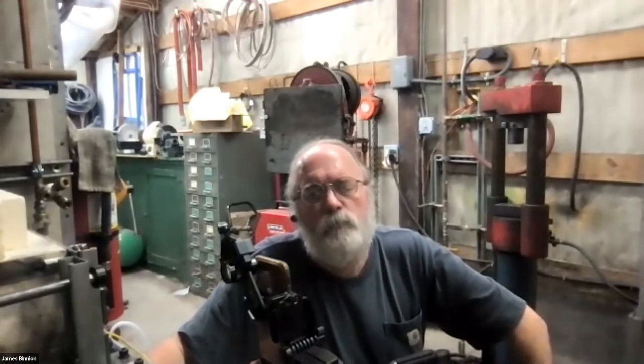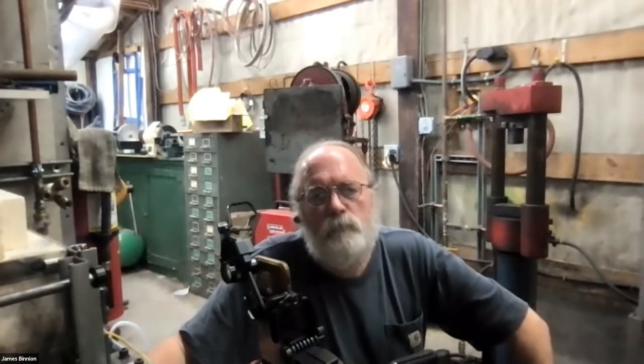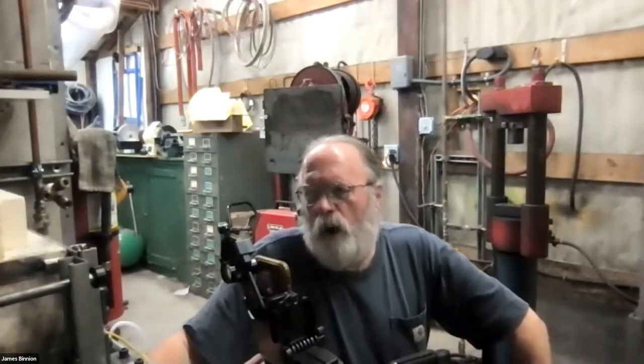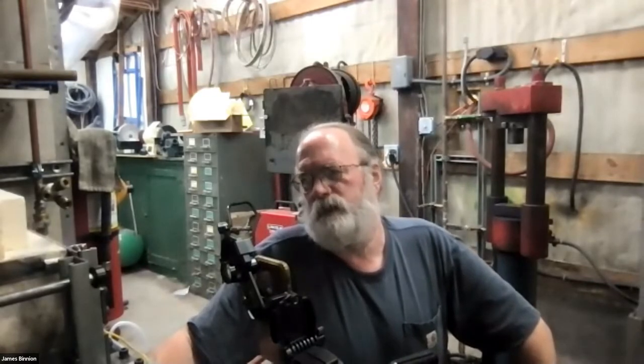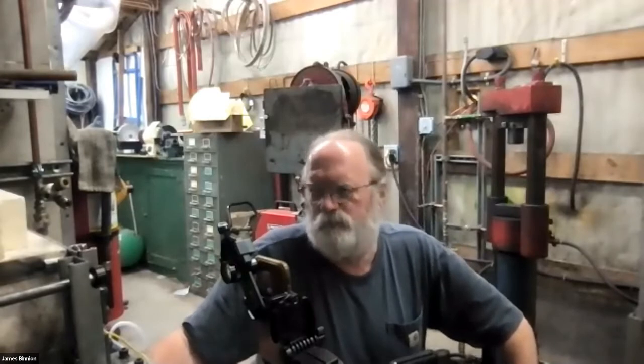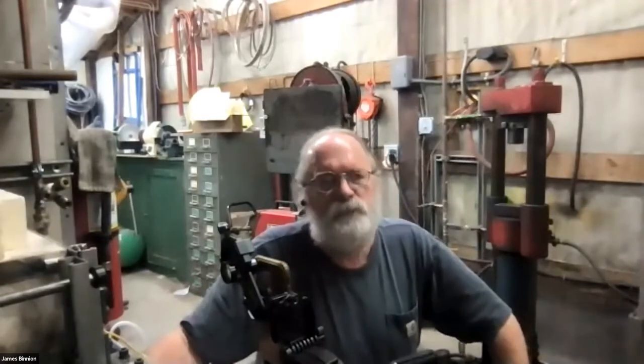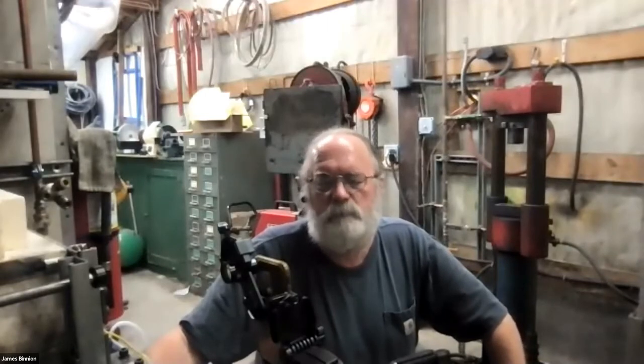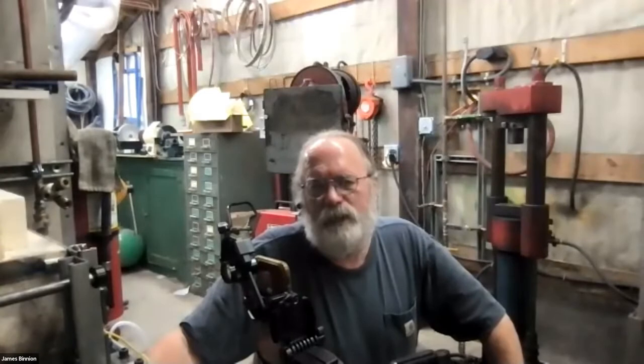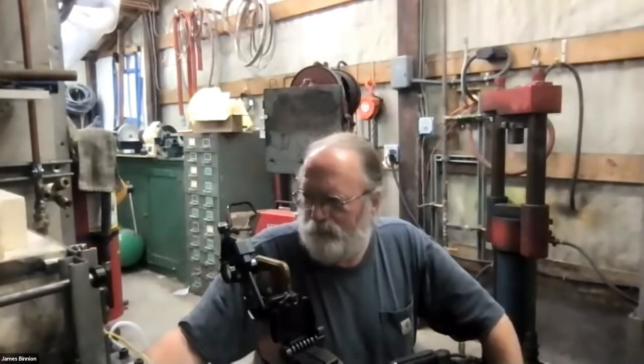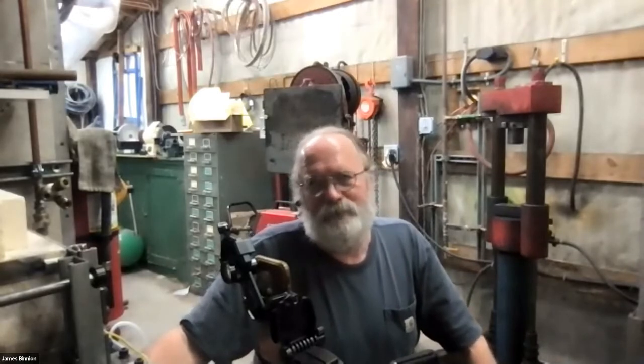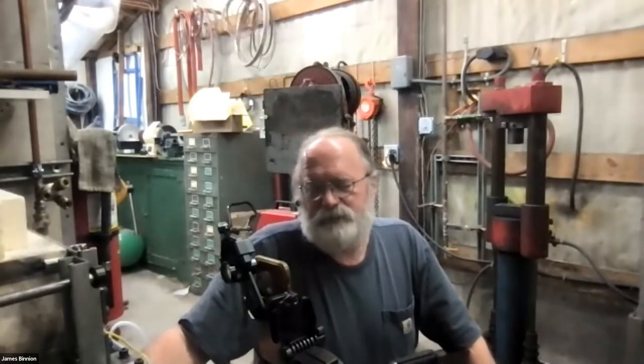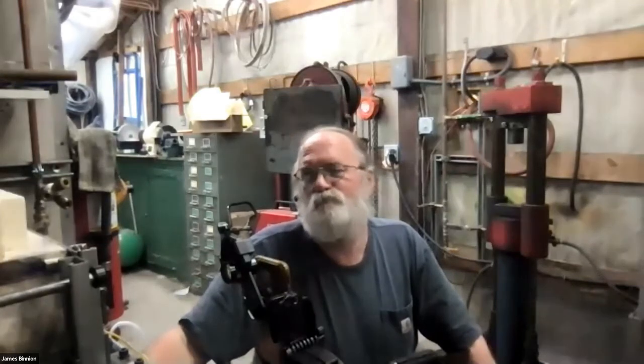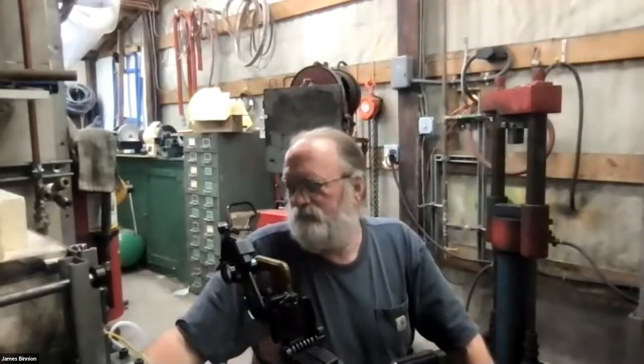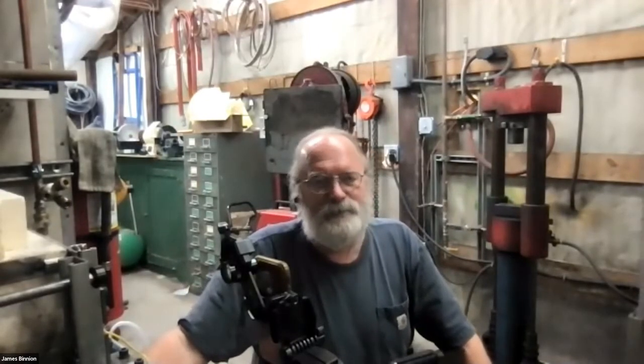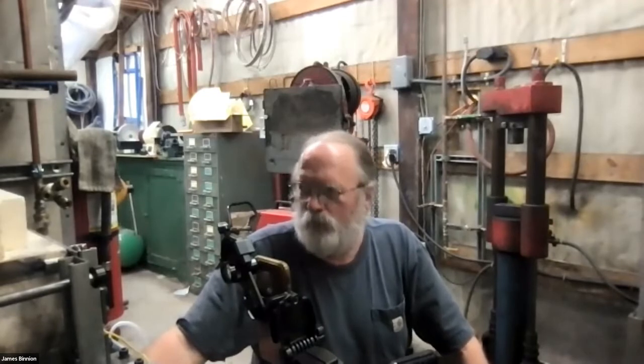About how big are the billets that you run in your, you know, you said that these are small billets compared to what you're normally making. What size would they usually run? Well, normally when I'm doing copper brass type billets, I'm doing like 2 inch by 3 inch by maybe a 2 inch thick billet. When I'm doing precious metals, a lot smaller than that, like 5/8 by 1.25 by 5/8. And at today's precious metals prices, that's a $3,000 to $4,000 billet.